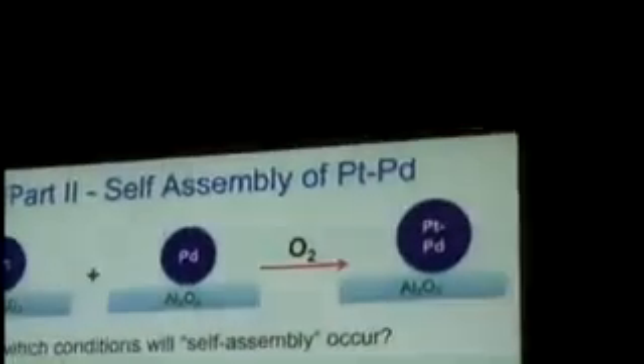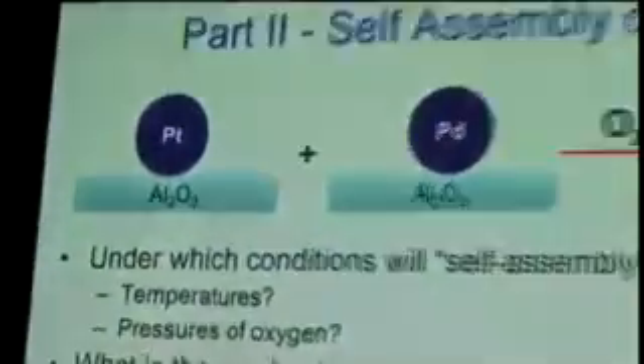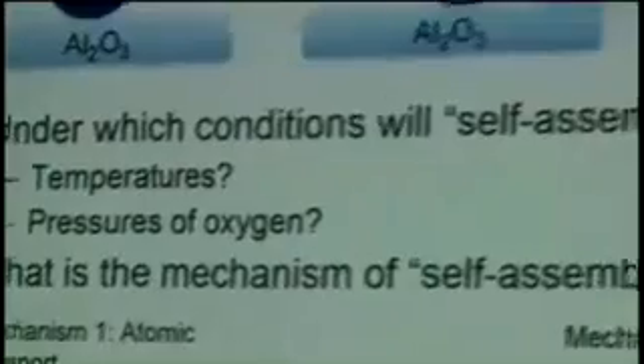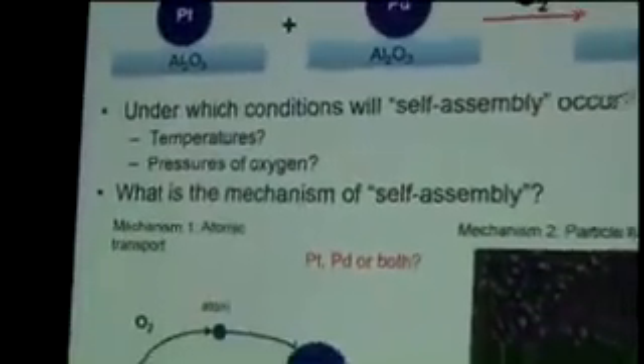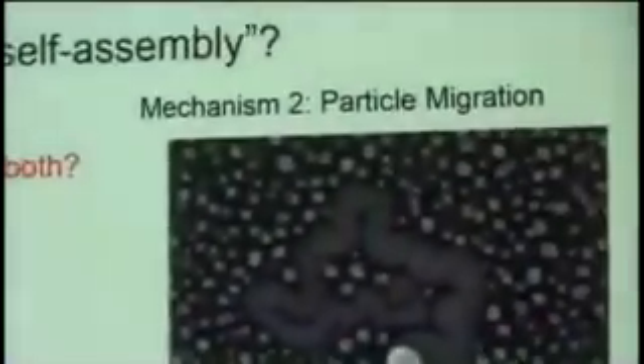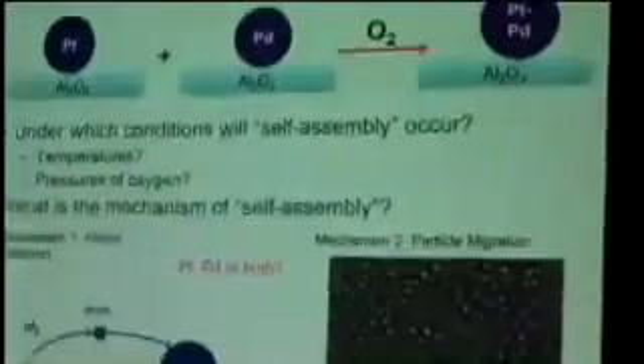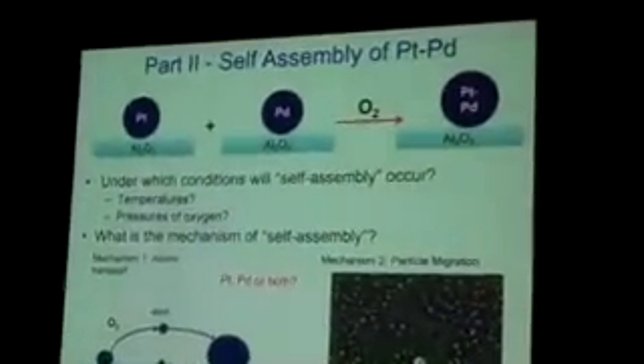Now the second part, how these self-assemble in a real catalyst. So we wanted to know if you take platinum on alumina and physically mix it with palladium on alumina and heat it, how do they form these particles? Now you might think there could be particle migration. That is just a teaser, because this really doesn't happen. So this is an artifact. You only see that if you have a reactive substrate, and we talk about that later. So other than the liquid phase, where there may be some particle migration, you don't see much particle migration.